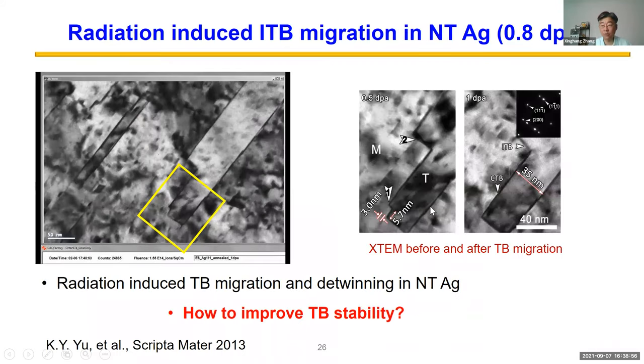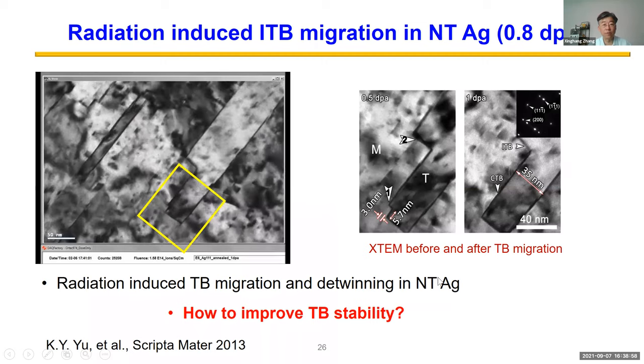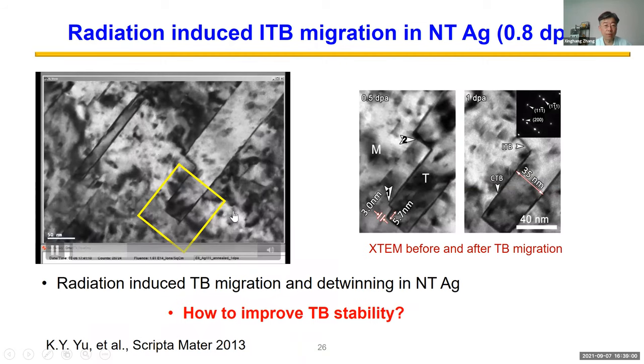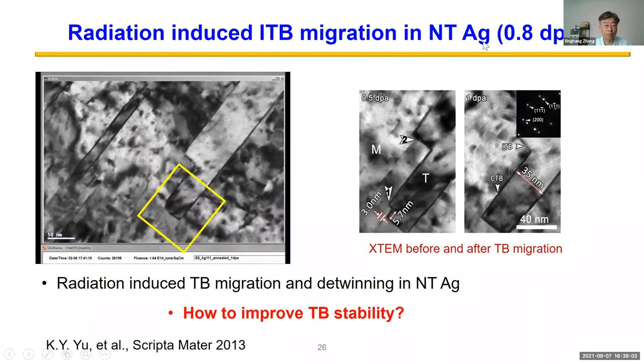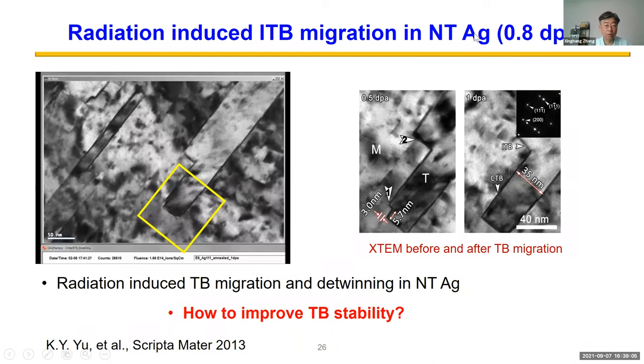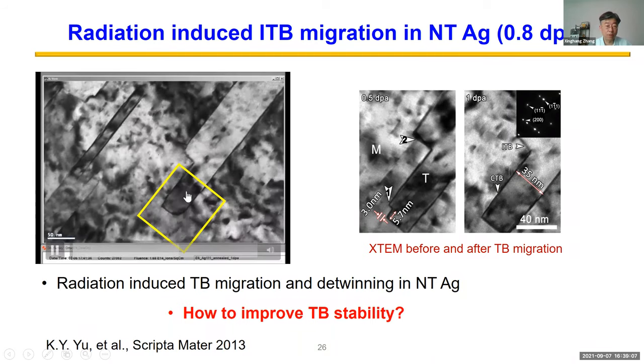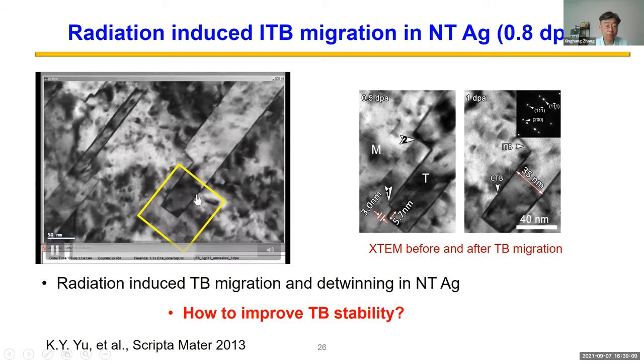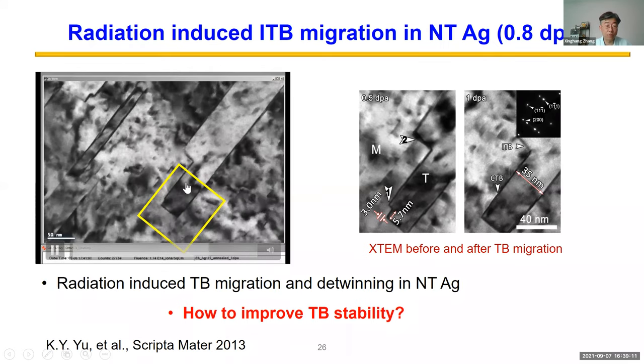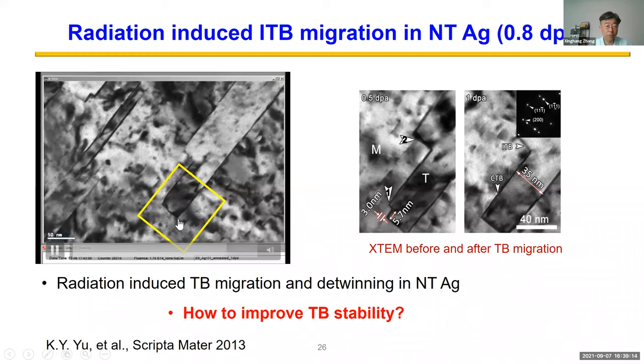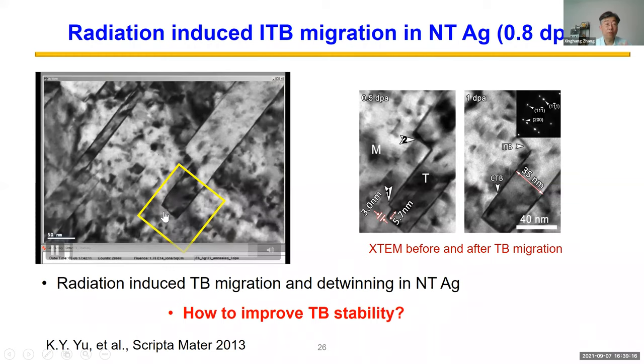Another thing I want to touch upon, this is quite interesting. This is on radiation-induced twin boundary migration. So now we're looking at nano-twin metal, but it's silver, another low stacking fault energy metal. What we're looking at here in the yellow box, this is a twin boundary, used to be very sharp, but during radiation, this twin boundary really evolved quickly.